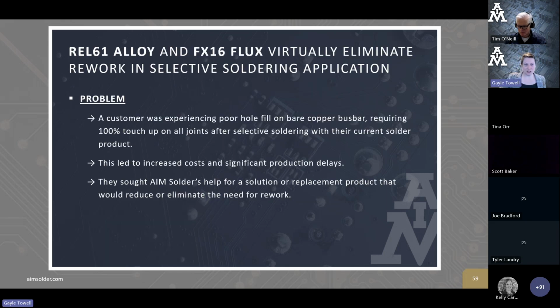So this was a selective soldering application. In this case, it was REL61 and our FX16 flux, which is designed for selective soldering and wave applications. They had poor hole fill on their bare copper bus bar. They had to touch up pretty much every joint after selective soldering, which, as you can imagine, really slows the production process down. So costs were going up, up, up. And they wanted help. What can we do about this?